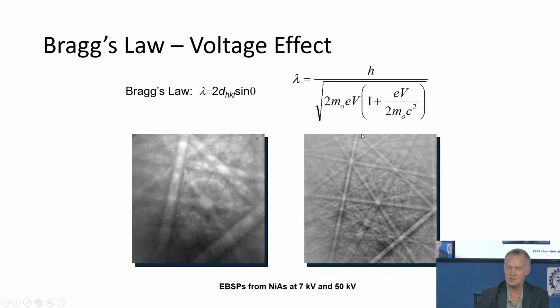This one up here is the same as this one up here. It's just this one was taken at 50 keV, this one was taken at 7 keV. So lower energy on this one, higher energy on this one, and we get a difference in what the pattern looks like. So if we're trying to measure D-spacing, we would have a little better chance here.